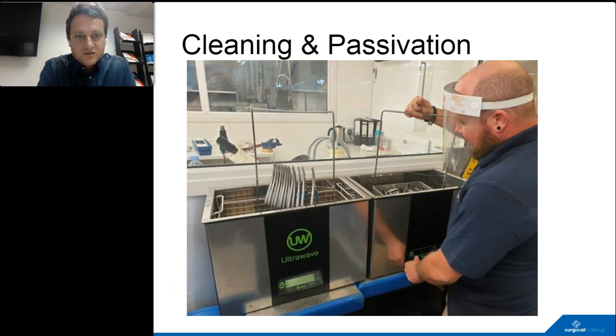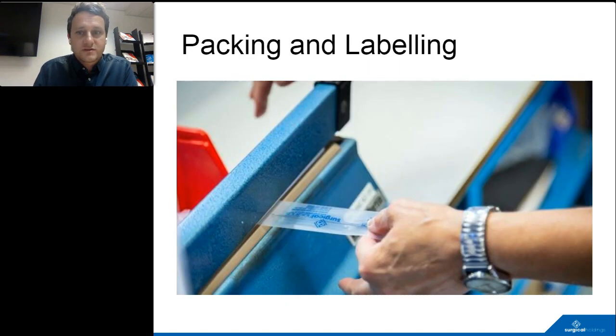Here are a couple of our tanks that we've got, obviously cleaning and passivation. We ultrasonically clean using the cavitation bubbles in the ultrasonic cleaner to ensure that the devices are really clean and manufacturing debris removed. And then we passivate. And I've mentioned passivation previously. It is a natural process, but you can artificially achieve this by using an acid, so nitric or citric acid. We tend to use citric acid. And that's what we're doing here, and that will oxidize the surface of the steel to achieve that corrosion resistance. And that's validated to an ASTM standard, actually. So it could be worth looking at that if you're interested.